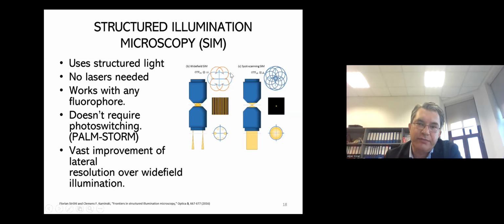But if you shift the whole thing, right, left, then some portions, for example if it is shifted right, some portions over here, which are actually high frequency portions, now become accessible to your instrument because they are shifted, so they come towards the DC center of this frequency space. That's the idea. Then you do this in 9 directions. When you do this in 9 directions, more high frequency components become accessible. This way you achieve a better resolution.